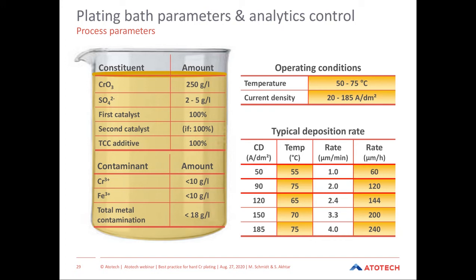The contaminants in the chrome baths are usually trivalent chrome, which is formed as a byproduct during the plating, and iron, which is usually coming from the steel parts from the etching process. We recommend to have no higher total metal contamination than 18 grams per liter. From that level on, the performance of the layer and the performance of the plating is going down significantly. We usually operate at 50 to 75 degrees centigrade.